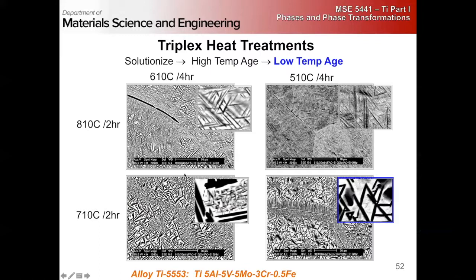Where's that poor ductility coming from? Essentially, we've got a whole bunch of tiny, tiny little grains here. We don't have any easy way for plasticity to occur. We've got huge Hall-Petch effects, and then these alpha laths all have a huge degree of plastic anisotropy, and they're all pointing in different directions. So you somehow need to coordinate deformation in all of these different pointing directions to be able to get any significant amount of plasticity out.